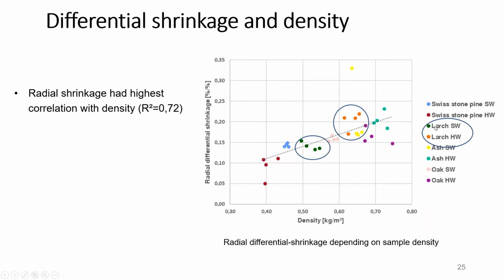Because I mentioned larch a couple of times, I highlighted the larch here. And it says softwood, the lower density, and the hardwood. Quite interesting that they are quite different, because early wood and late wood are softer than hardwood. The larch hardwood extractive content can be very high, as we have investigated a few years back, because of arabinogalactans and phenolic extractives. It could be up to 30% of mass ratio in the hardwood. Not the case with these samples, but the hardwood extractive content could be very high, and this would all be contributing to the sorption behavior.